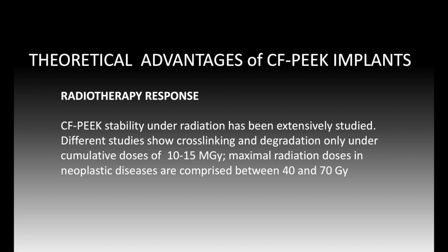And from a radiotherapeutic point of view, there are also some advantages. For example, the stability of the implant, because this implant is stable and does not degrade until cumulative doses of 10-15 megagray.